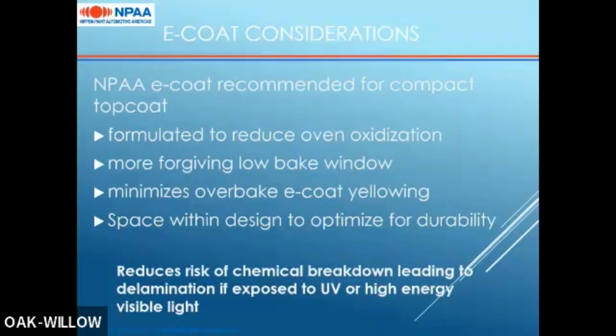We recommend an e-coat that's been designed for compact top coat. The one that we provide is formulated to reduce oven oxidation. It's more forgiving at a low bake window, minimizes overbake for e-coat yellowing, and there's space within its current design to optimize for further durability if needed. All of these combined help reduce the risk of chemical breakdown, leading to delamination when exposed to UV or high energy visible light. So while our top coat is designed to prevent light penetration to the e-coat layer, the additional protection from the e-coat helps protect the substrate.